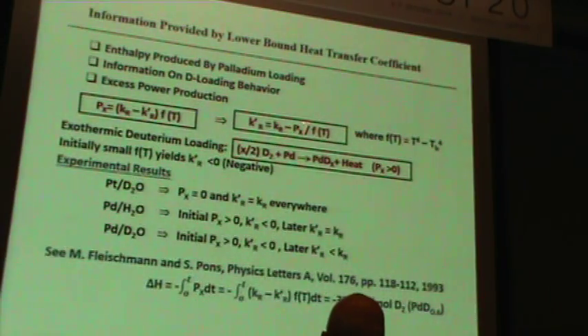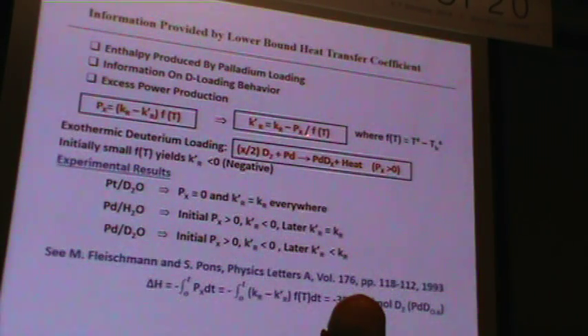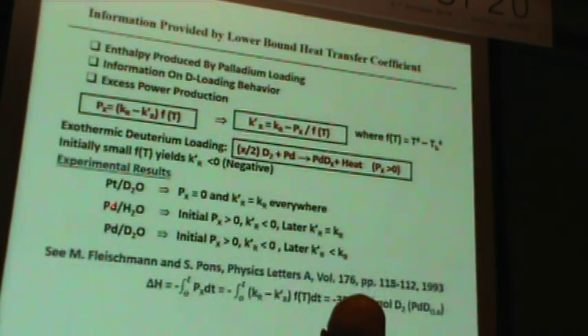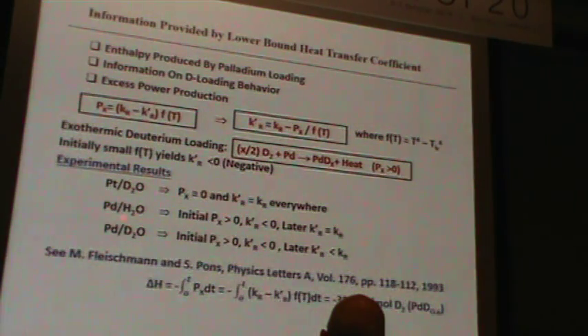If you have some excess power, and early on you have excess power due to loading. So you get that with palladium in water, regular water, or heavy water. You don't see that if you use platinum, because there's no loading early on. And you can get information about the loading, the heat of loading, from your experiment.